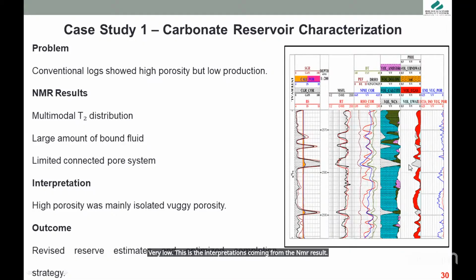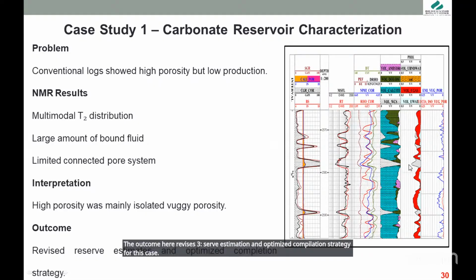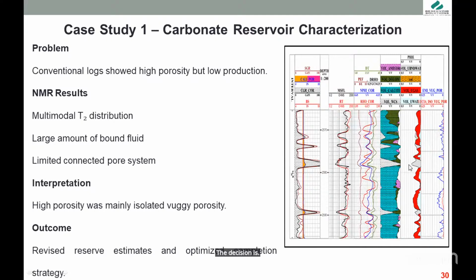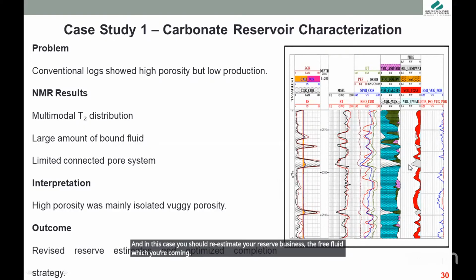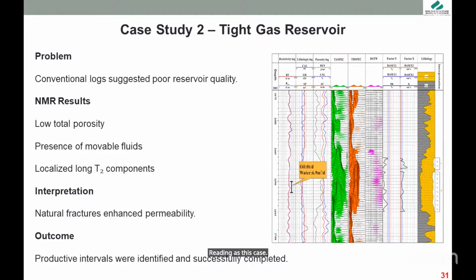The outcome here: revised reserve estimation and optimized completion strategy. For this case, the decision is to please revise your reserve estimation, because the reserve estimation is built on the total effective porosity with capillary bound and the free fluid. In this case, you should re-estimate your reserve based on the free fluid, which is coming from the NMR reading. Now we will go to case study number 2.